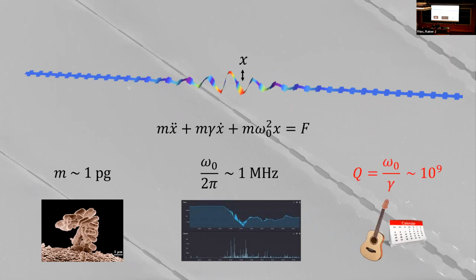The really peculiar property of this device, however, is its damping rate. So this oscillator is really well decoupled from the environment. And you can characterize that as the ratio of the frequency of vibration to the energy damping rate, something we call the quality factor. For this device, it's around 10 to the 9. So this is the first mechanical resonator ever at room temperature with a quality factor of 1 billion.